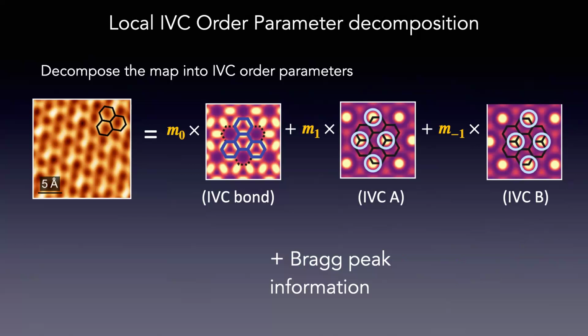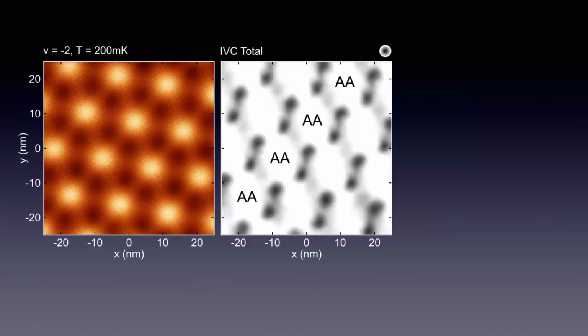Okay. So what you do is you take data like this, and you bin it up in small little regions, and in each region you extract these order parameters. This sounds simple, except it's very complex, because when you do your FFT, you need to make sure that one corner of your image knows exactly where the center of the hexagon is in the other corner of the image. Otherwise, the phases do not mean anything from one place to the other. So this took a lot of difficult work to find all the atoms in this picture first, and a lot of coding by the theorists and a lot of checking by experimentalists. The result, at the end, was that we could extract these order parameters.